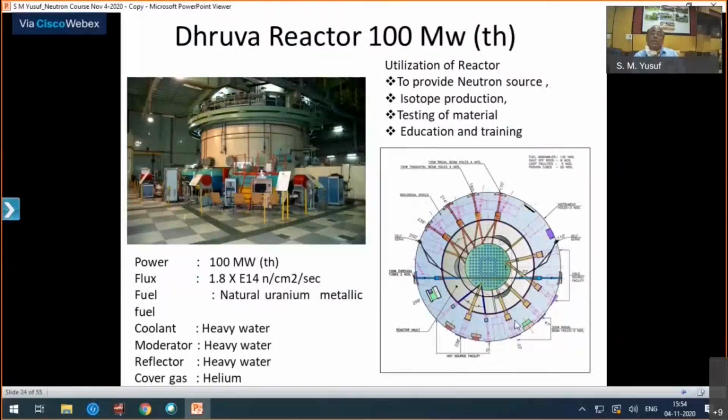Why? Because we are interested in studying materials, where, whether it is crystalline or not, the typical atom-atom separation is 1 angstrom. So we need a probe which can measure that kind of length scale. So atomic separation length scale, planar separation length scale. That's why we need milli electron volt kind of energy scale. Okay, and that milli electron volt energy is also suitable for measuring magnetic excitations.